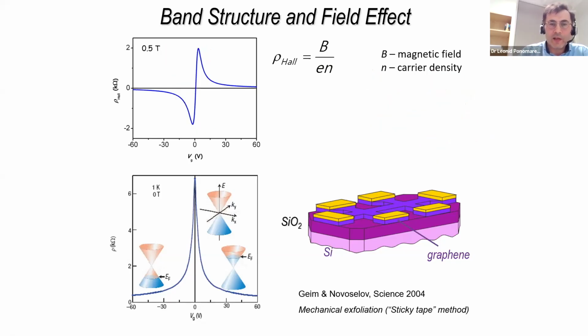So before answering this question, I would like to also add that we can actually prove that we have different types of charge carriers, electrons and holes, by measuring what is called Hall resistance. So normally we apply current along the Hall bar and measure a voltage also along the Hall bar. But if we measure voltage between two contacts which are on the opposite sides of the Hall bar, this is called Hall resistance. This Hall resistance tells us two things. First of all, the sign of the Hall resistance, positive or negative, will tell us if it's electrons or holes. And second, the value of the Hall resistance will tell us how many electrons we actually have in our conducting material, the density of charge carriers.